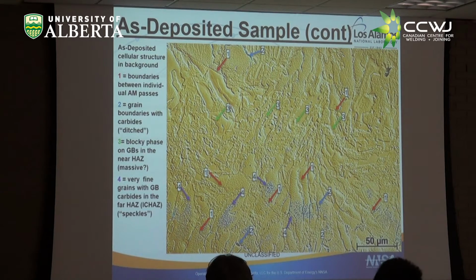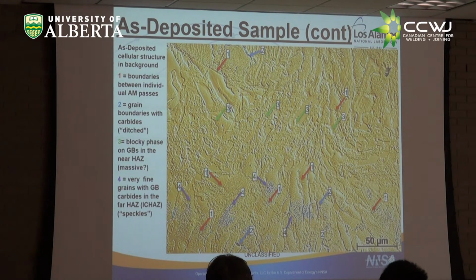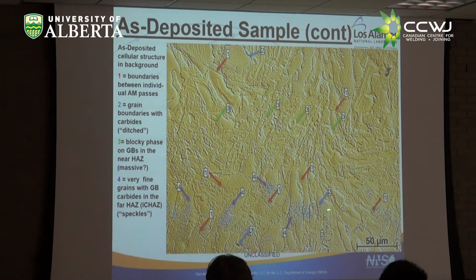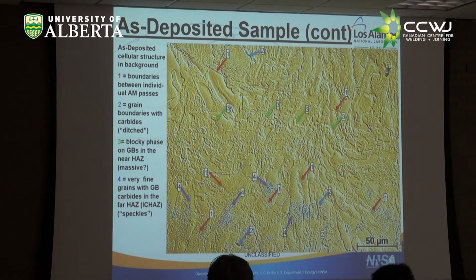There's also this blocky phase. So here, a featureless kind of blocky phase. That ends up being in the near heat affected zone. I'll tell you how I got to that conclusion in a minute. And then there were these little fine grain regions here. I think I can barely see that here, but all this purplish looking stuff, these little fine speckled regions, that ended up being in the far heat affected zone. How did I come to that conclusion? I'll show you that in a minute.